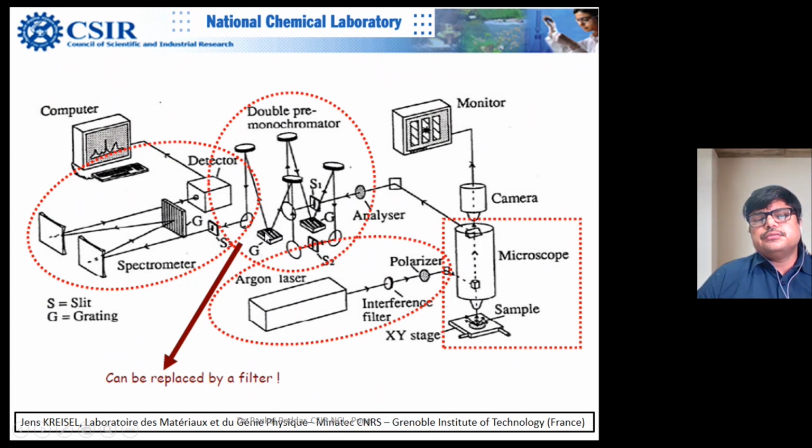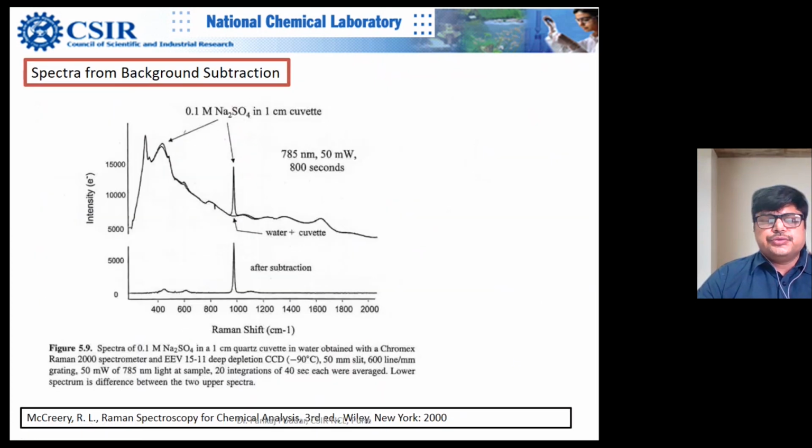And then even the resolution of the spectrophotometer becomes better. So instead of 1 centimeter inverse, which will be the case for subtractive triple monochromator, in an additive spectrophotometer you can get resolution down to 0.1 centimeter inverse. This is really amazing. So I will show some examples.